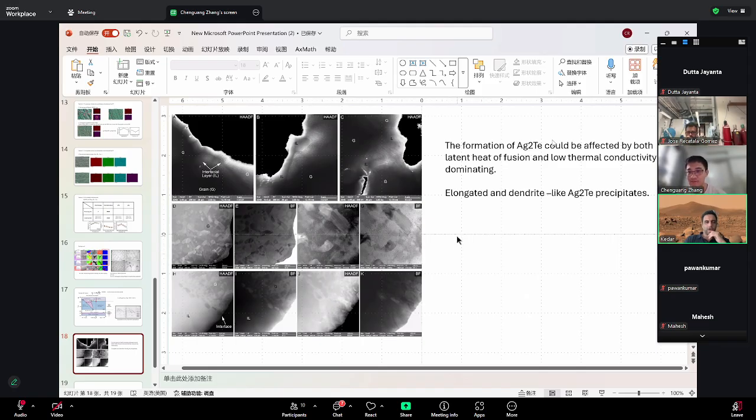Yeah, so this is ongoing work, but I think the only thing you need to look at is solid fraction, or fraction of different phases, as a function of cooling rate. There must be people that studied something. It might require some funky tool. Okay, so Haiwan's question: you cannot do it in XRD because the XRD sample stage cooling rate is fast, but you have a thermal mass from your sample. You cannot suck that much heat out of grams of sample. Powder may be okay, right? So if you want to look at powder, maybe that's possible, not a pellet.